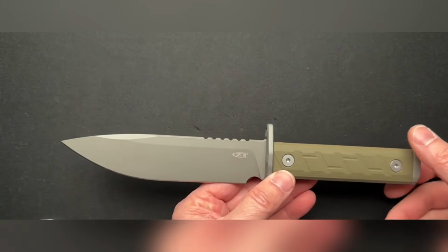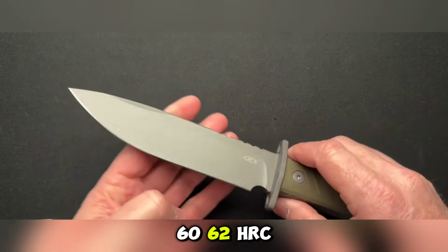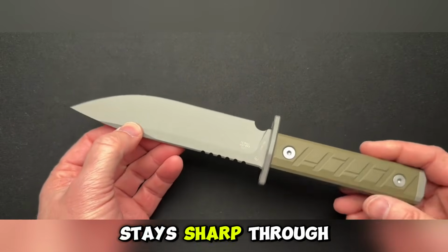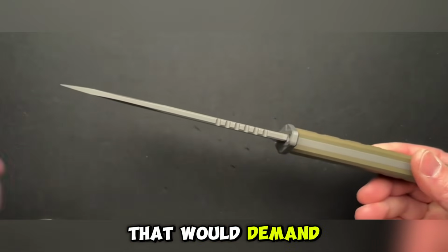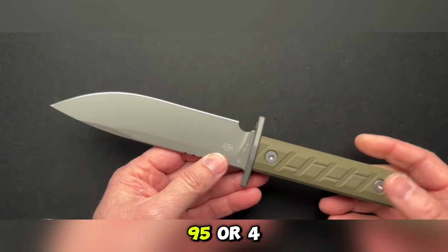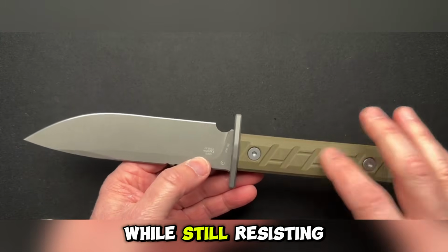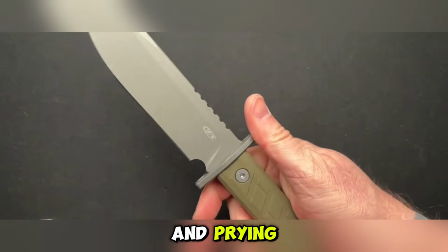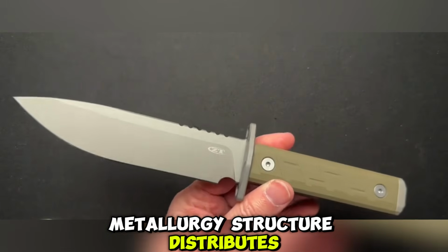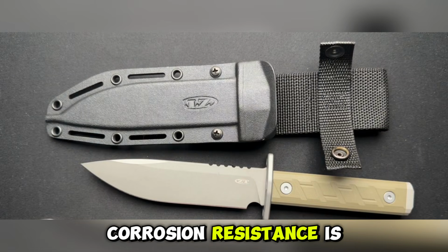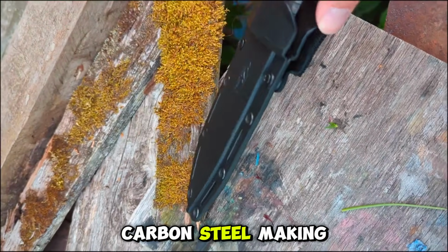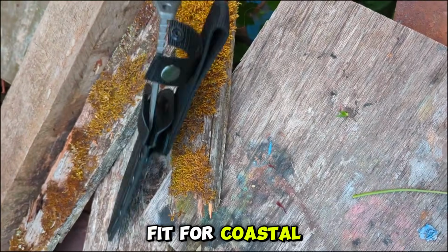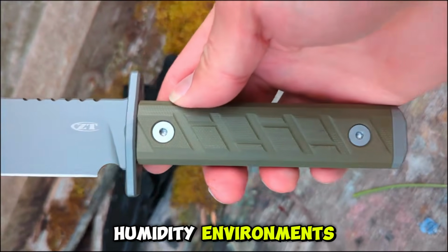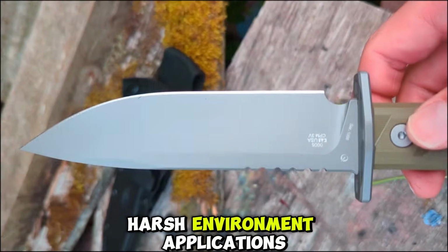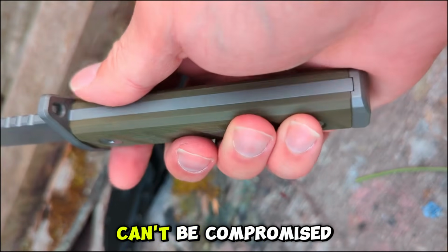ZT heat treats it to 60-62 HRC, an edge that stays sharp through weeks of hard field use that would demand multiple resharpenings from 1095 or 420HC blades, while still resisting chipping under hard chopping and prying, because the powder metallurgy structure distributes stress evenly instead of concentrating it at grain boundaries. Corrosion resistance is significantly better than plain carbon steel, making it a strong fit for coastal, jungle, and high humidity environments. Built for the most demanding harsh environment applications where performance simply can't be compromised.